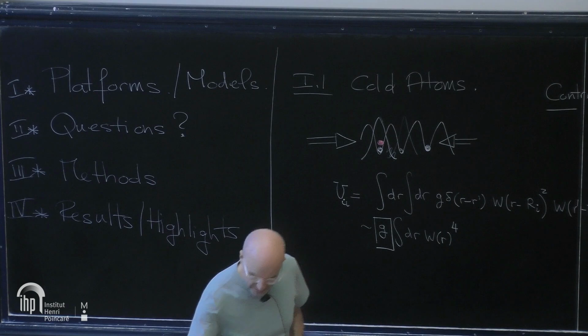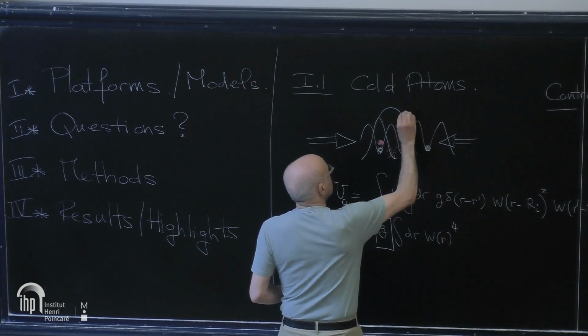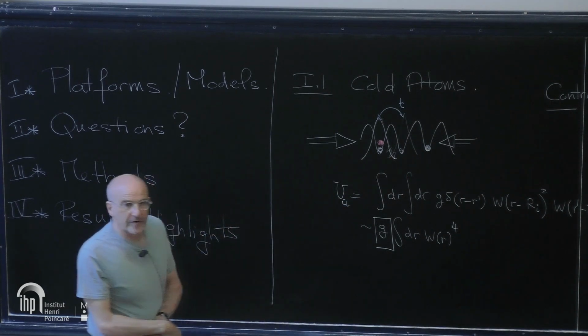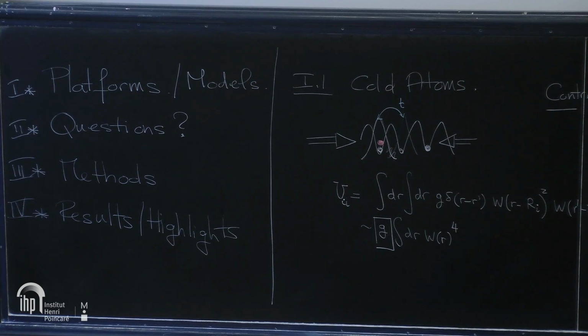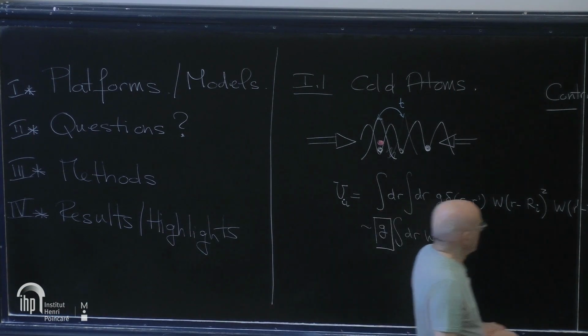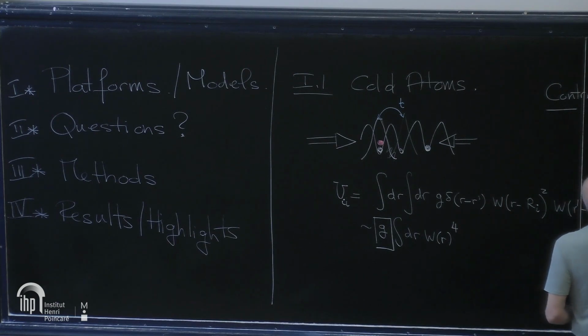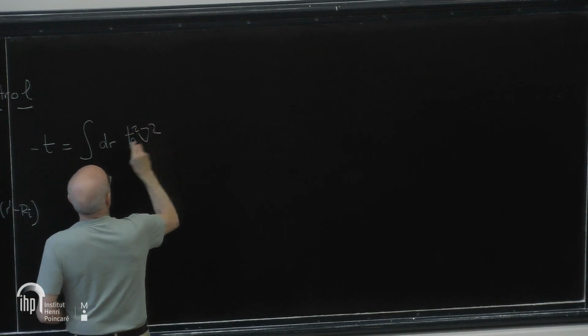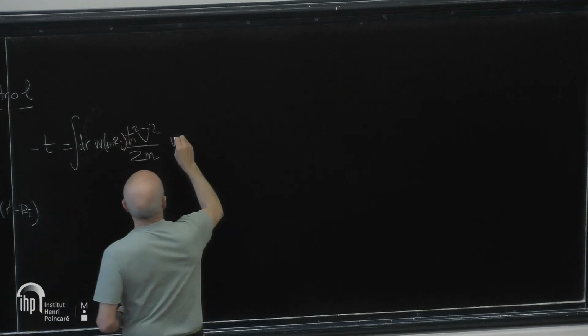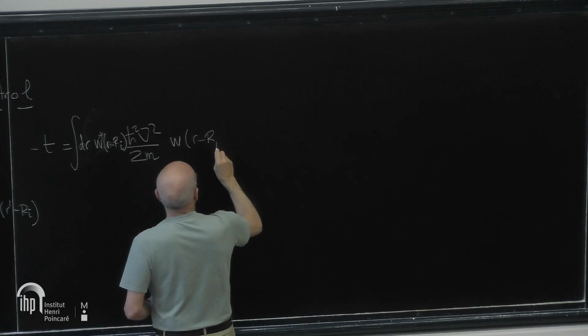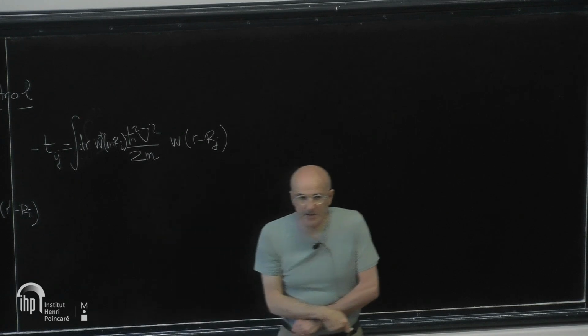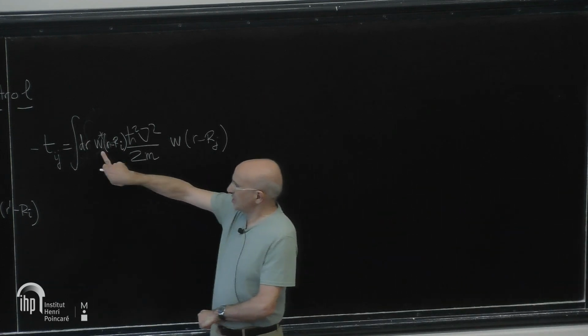Similarly, the hopping amplitude, which I talked about a little bit earlier, which is the ability of the atoms to hop from one well to the other by the tunnel effect, hence the amplitude being called t, like tunnel, is going to be something like the integral of the kinetic energy taken between two Wannier functions located at sites R_i and R_j. And that would be t_ij between two lattice wells. So this can also be tuned, mostly by changing the extent of the Wannier function and hence the power of the lasers.